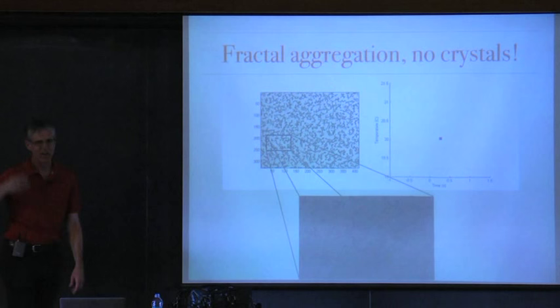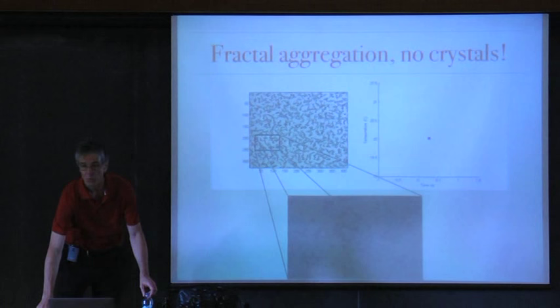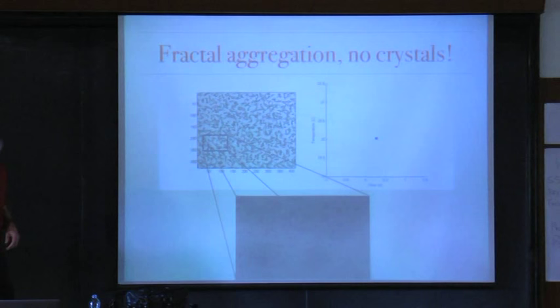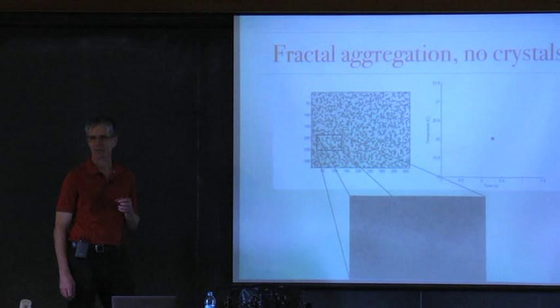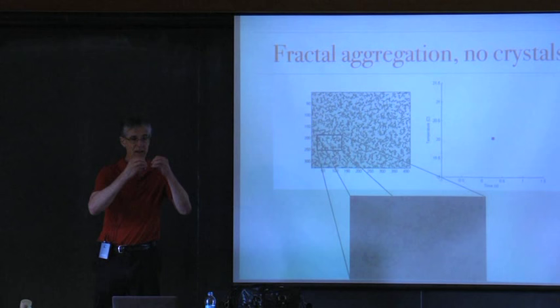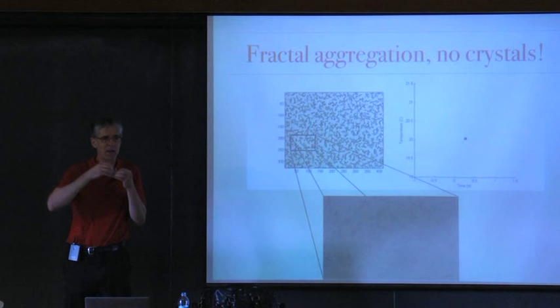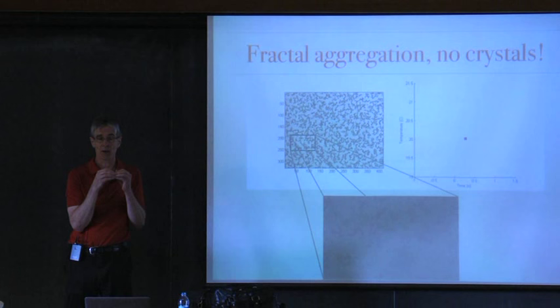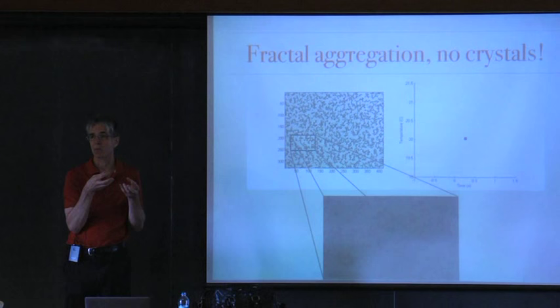I've held something back — a sort of dirty little secret. The part we're not so happy about is that these DNA-coated particles make fractal aggregates. We don't want fractal aggregates — we want crystals. They make fractal aggregates because when they come together and hit each other, they stick there and won't roll. If you want to form a crystal, the particles need to make small rearrangements to maximize the number of bonds — that usually lowers the free energy — but that's the equilibrium state only if the particles can roll. They can bind and unbind just fine, but...